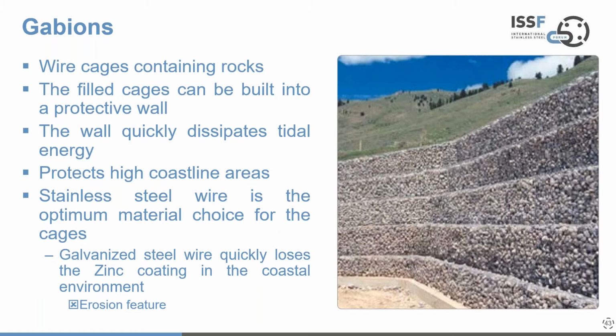One of the things you have to remember is that, because these cages are built from a wire structure, they're subject to both erosion and corrosion. The rocks move around in the cages. When they hit with the seawater, they'll settle over time. So with a coated material, something like a galvanized steel product, you will lose the zinc coating, primarily through erosion. So you need to choose a material for these applications that is going to hold the rocks in place for a long time. And again, stainless steel wire is the optimum choice, because then it's a fit and forget feature.